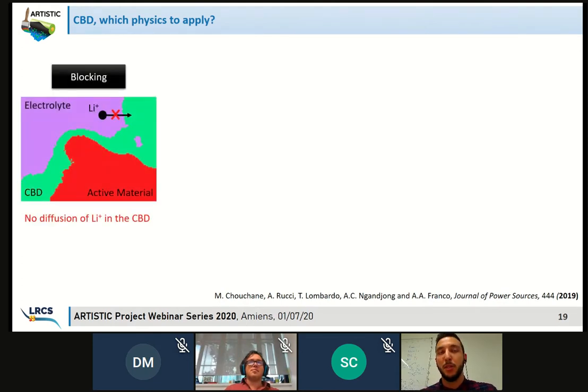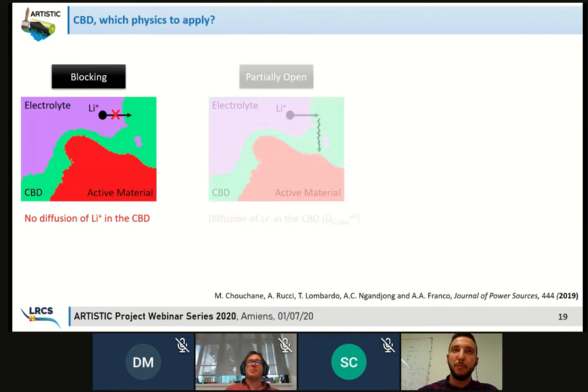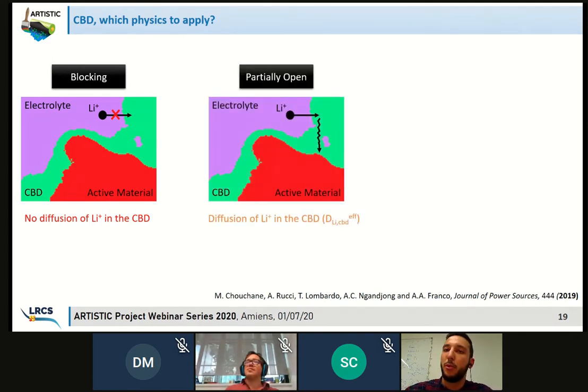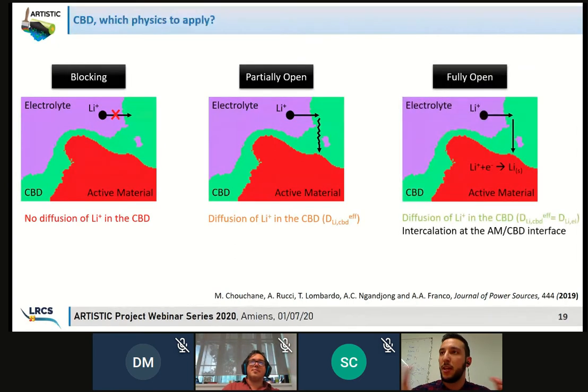The first one is that the CBD will be blocking for lithium ion, which means lithium ion will not be able to diffuse into the CBD. Then a partially open hypothesis, where the lithium ion is allowed to travel through the CBD, but with an effective diffusion coefficient, based on its tortuosity and microporosity. And then the fully open case, which consists of treating the CBD as electrolyte. The lithium ion can diffuse as fast as in the electrolyte, and can also intercalate at the interface between active material and carbon binder.